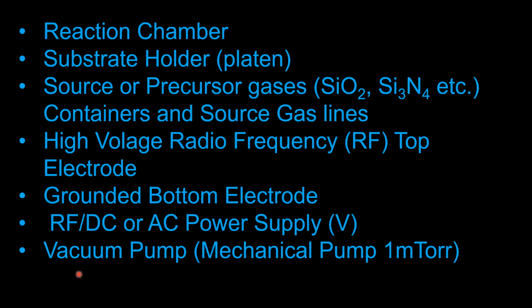The PECVD system is connected with a vacuum pump. You basically need a clean environment to deposit a thin film inside a reaction chamber. And in order to achieve a clean environment without any collision of gaseous molecules inside the reaction chamber before they reach the substrate, the environment of the reaction chamber is cleaned by using a vacuum pump, which basically evacuates the reaction chamber up to 1 millitorr to a few torrs. And the pump which is used in a PECVD system is usually a mechanical pump.